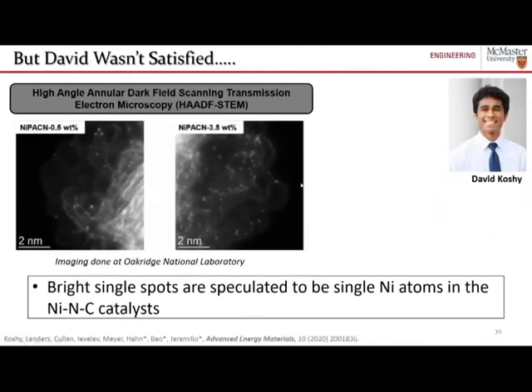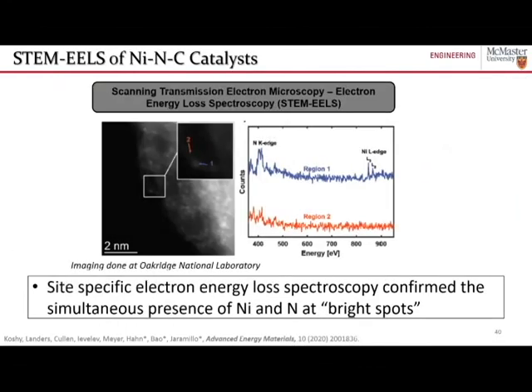But David wasn't satisfied, and so what he ended up doing was taking his materials to Oak Ridge National Lab and being able to use high-angle annular dark field scanning transmission electron microscopy, so a mouthful there, to see these bright spots that we attributed to being nickel in these catalysts, but then actually using EELS spectroscopy to see that both nickel and nitrogen were present at these locations. So pointing once again towards the fact that nickel-nitrogen coordinated species are the active site structures in these materials.